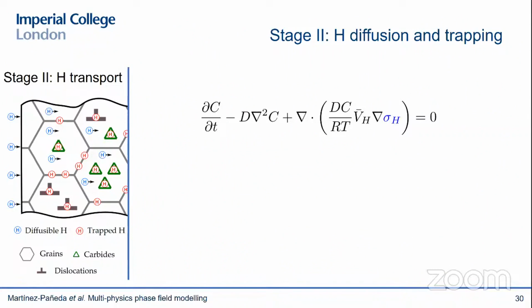And this coupling with the mechanics is quite important in my opinion, because if you take, for example, the steady state solution of this equation, you end up with something like this. So you have a hydrostatic stress term inside of an exponential. So what this obviously means is that whenever you have a stress concentrator like a crack, your concentration of hydrogen is going to be much, much higher. So this is a key element that you don't want to miss in your model.